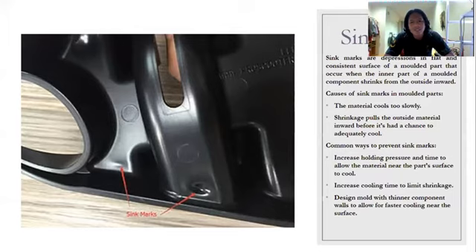So the next defect is sink mark. Sink marks are depressions in a flat and consistent surface of the molded part that occur when the inner part of the molded component shrinks from outside inward. The main cause is the material cools too slowly, and shrinkage pulls the outside material inward before it had a chance to adequately cool.